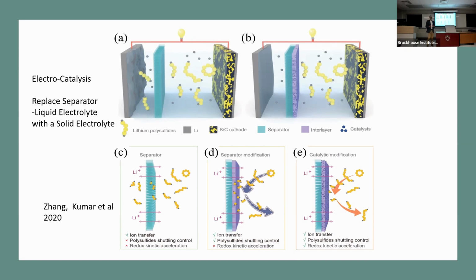Yeah. So if you have 100 microns, the resistance is so high, it will not conduct until it reaches a temperature of 150 degrees centigrade. The batteries have to work at 150 degrees centigrade. It's possible. That's not impossible. But yeah, that may be another solution. Or you can combine these ceramics with polymer and make composites, containing both lithium salt and the ceramic. So that is the direction in which it's moving at the moment.